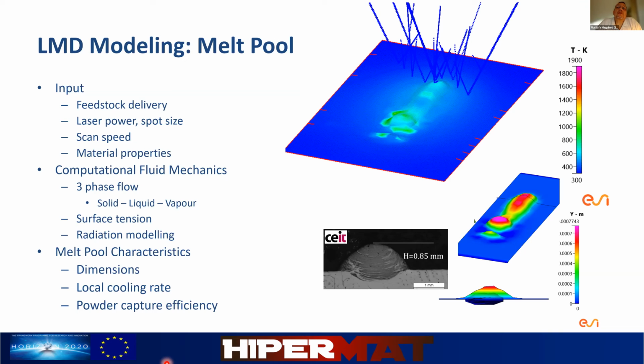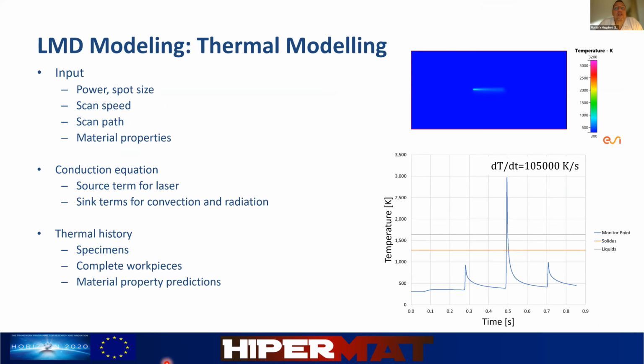We run the melt simulation until we get a quasi-steady deposited line. And at the end of that line, we extract the data we would like. Data would include things like melt pool width, height, and depth. Here in this case, Sergio furnished us with some very nice validation data. For one set of parameters, you see here a height of 0.85, while the simulation is predicting 0.77. So quite close, not exactly the same, but quite close. And the trends, you will see the trends in the next slide. In terms of width, it's really dependent on the spot size, and we will see more of that later on.